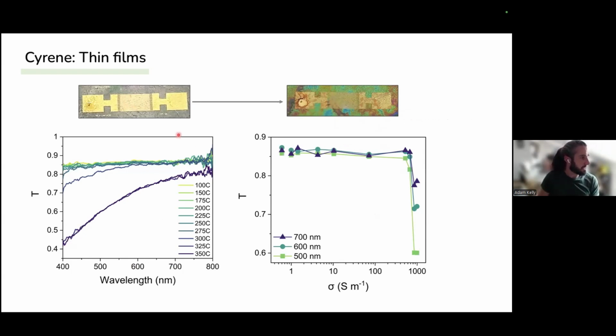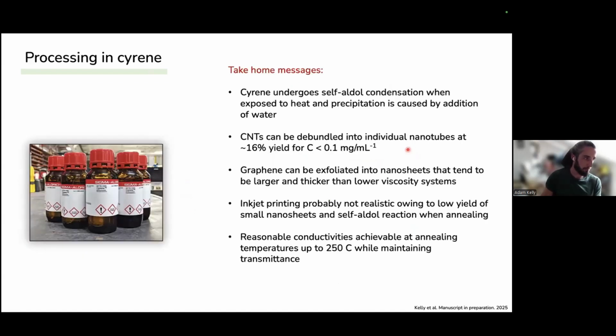So we also looked at the transmittance because people use carbon nanotubes for transparent conductors. And this is actually pretty interesting because as you increase in temperature, it doesn't begin to affect the transmittance too much up until you reach values of maybe 300 degrees. So the conductivity is relatively constant. It's slowly growing until this self-aldol condensate begins to turn black. But we can achieve conductivities of about 500 Siemens per meter while maintaining a reasonable transmittance.